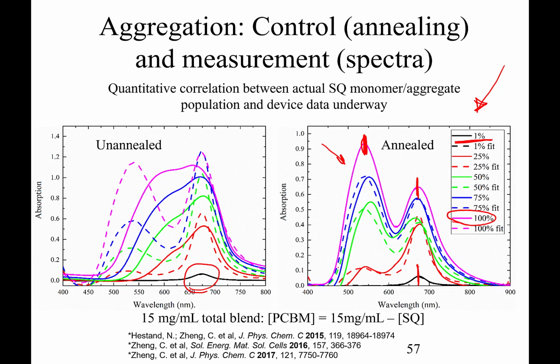You'll see these dotted line fits in here. The green one that you can see right here is basically a fit of the purple line in here, this annealed spectrum, and the black line down here, summed together to get a fairly decent description, which is really a little bit of the monomer and a little bit of the aggregate, and we can put those together and we can kind of quantify how much aggregate we've got and how much monomer we've got. The problem is when we work with the unannealed samples, when we try to fit in the same way, what we find is that we can't actually do it, right?